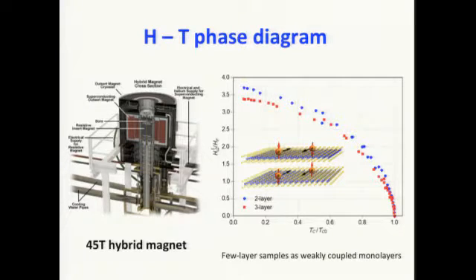Okay. In a multilayer case, are spins in neighboring layers aligned or anti-aligned? Anti-aligned. So in the bilayer case, you can think of the two layers as rotated by 180 degrees, right? When you look at the Fermi surface of the whole system, it's spin degenerate, but actually the spinors are locked to the layer. So it's a spin and momentum lock within each layer, and then the spins are also locked to each layer.